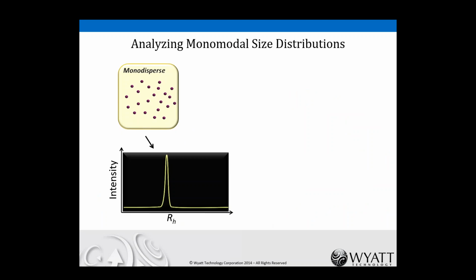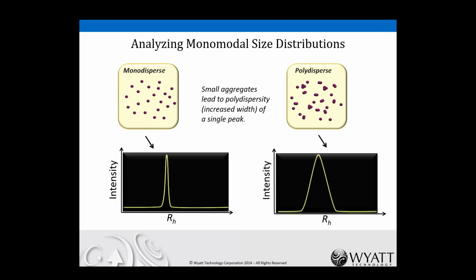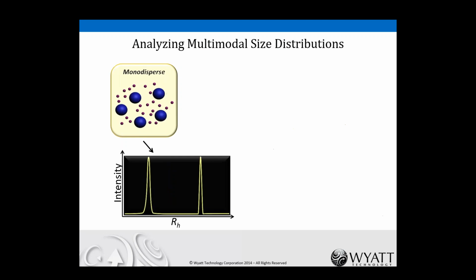Further looking at the analysis, so you might have in your solution a monomodal and monodisperse set of particles. Monomodal means that they are within a size range which is not resolved by dynamic light scattering, so they appear as a single peak. And monodisperse, of course, means that they're all the same size, and so that peak appears narrow. If the particles are polydispersed, for instance, due to aggregation, you might have monomers, dimers, and trimers. That leads to a broadening of the peak, and we call that broadening polydispersity. So the output of this analysis is actually the average size, the RH, and the percent polydispersity.